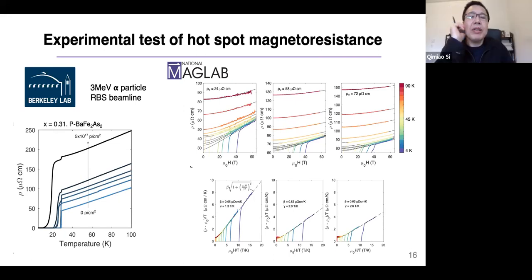So you do this analysis for the magnetoresistance, but it seems like if I look at the temperature dependence, as you change the disorder, that will affect strongly the cold region contributions, right? So I'm somewhat surprised by this linear resistivity slope that seems to be, to a zero order, not too sensitive to the amount of disorder, which I would not have expected this cold spot, hot spot model to describe that. Right.